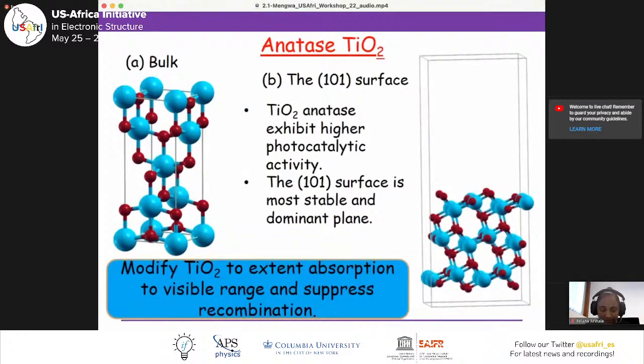Now, anatase TiO2 exhibits high photocatalytic activity. The bulk anatase TiO2 has a tetragonal lattice, while the 101 surface is the most stable and dominant plane. TiO2 has a band gap of 3.2 electron volts, and therefore it absorbs in the ultraviolet region, which constitutes 3 to 5% of the solar spectrum. Therefore, you need to modify TiO2 to extend absorption to the visible range.